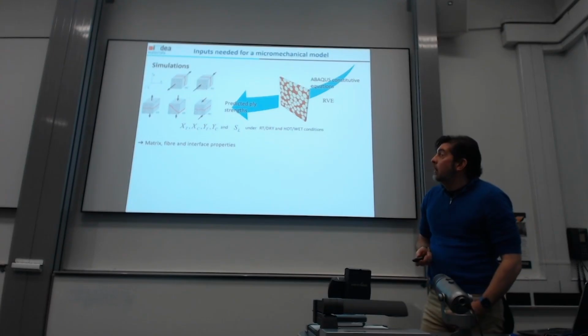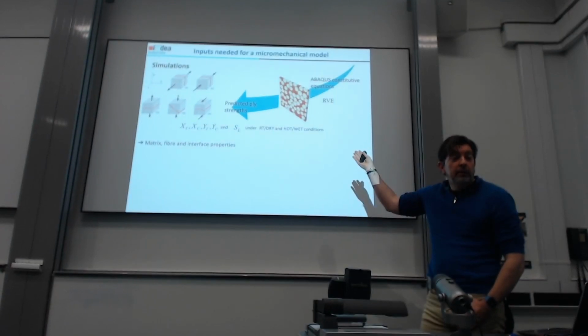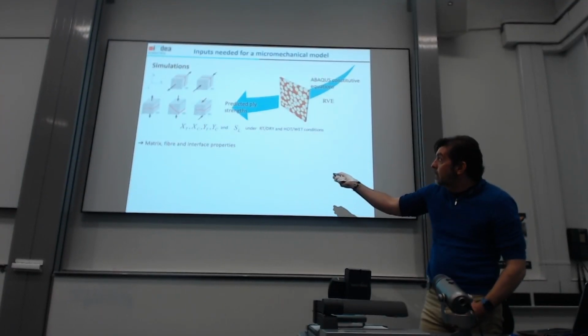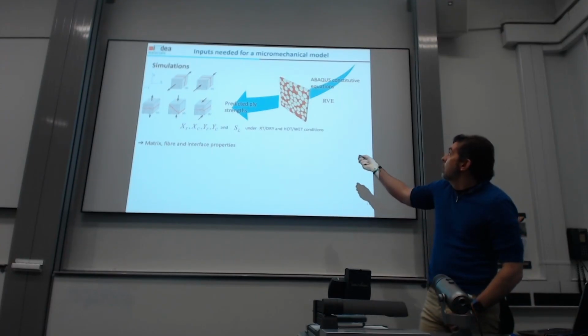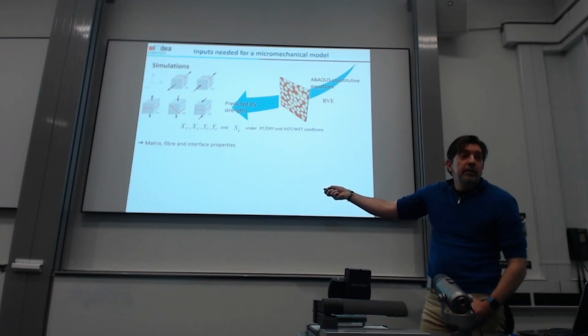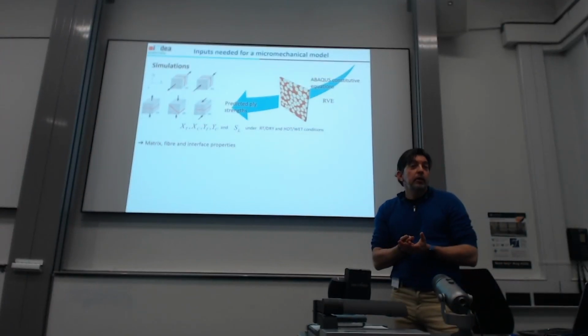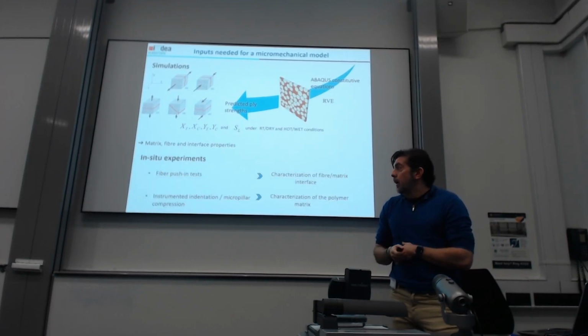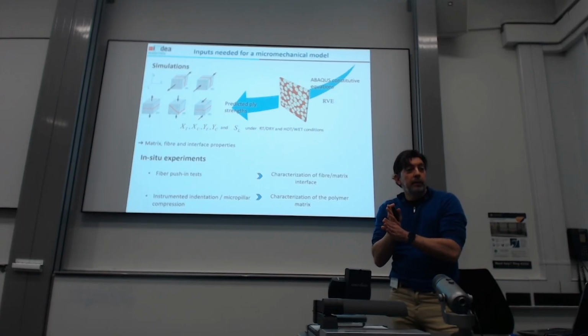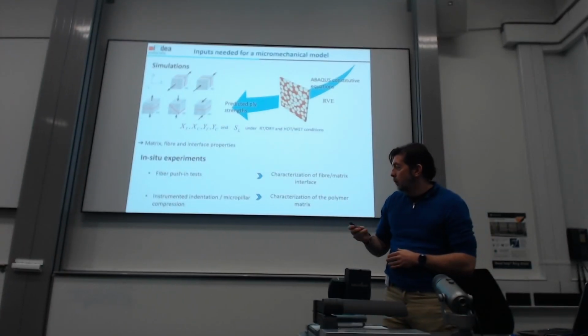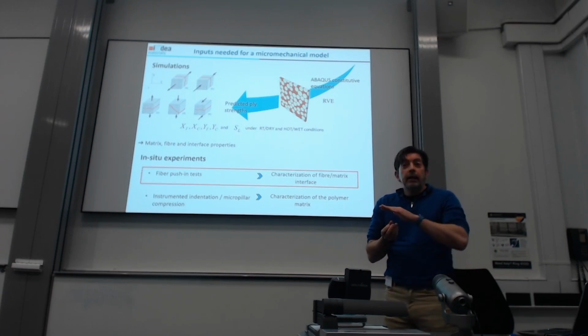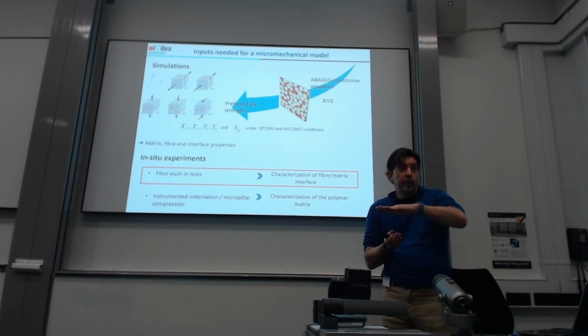What the simulation people do is construct a three-dimensional finite element model of the representative volume of the composite in order to predict the ply or the laminate strength. We need to fit this with the properties of the matrix, the fiber, and the interface. Some properties are taken from the literature, but some you really need to measure in situ in the actual laminate, in the actual ply. When I talk about in situ experiments, that means we are doing the experiments in the real composite, in the cross section of the real composite.